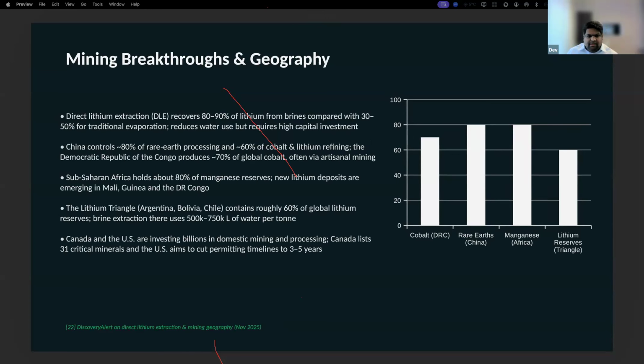In terms of mining, there have been a lot of technological breakthroughs and innovations happening. The most notable one is called direct lithium extraction, DLE, and it recovers 80 to 90% of the lithium from the brine solution, compared to 30 to 50% from traditional evaporation. Historically they just pump out the brine, just like how you extract table salt out of seawater, they extract lithium out of the brine solution. However, direct lithium extraction doesn't use that kind of method.